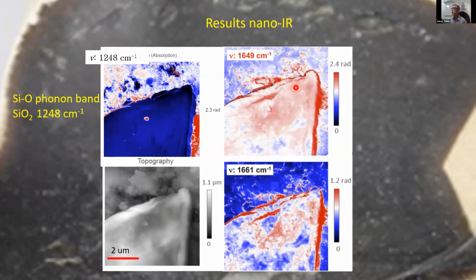Here on the right-hand side is the wavelength corresponding to the alpha helix. You see it more or less covers that area of the microinclusion. And down below is the area of the random coils that more or less overlaps, but you see the spatial distribution is more sparse, and it is of a lower intensity than the one above it. On the other hand, the peak for the silicon oxide shows that it's completely absent from the area of the microinclusion. Okay, so we have some chemical information here.